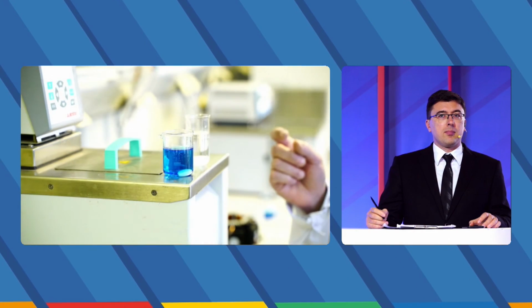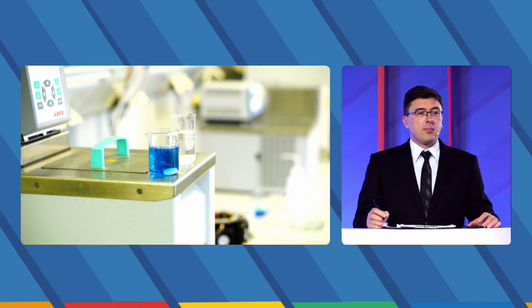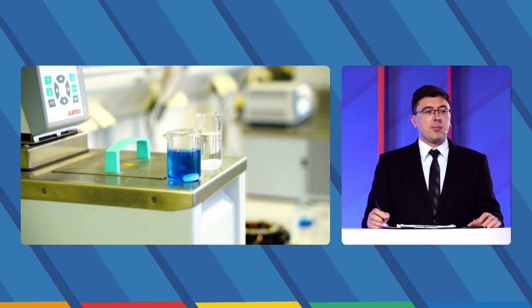One more question from India, from Swati Singh. What was the titanium dioxide dose that you used during the experiment? Yes, we used 100 milligrams of titanium dioxide per 25 milliliters of methylene blue solution. And following that, is there any adsorption on titanium dioxide? Yes, this is a very good question. We checked the adsorption experiment, but we did not find that it's active at this stage, because you can see this material in the solution has a white color, but if adsorption phenomena occurred, the color of the adsorbent would be blue.